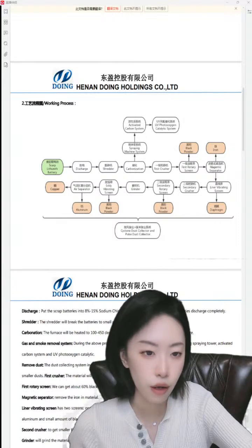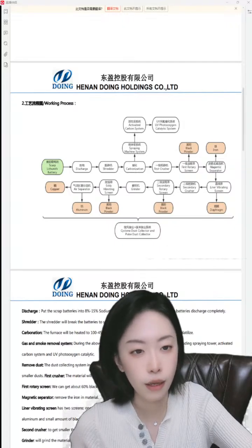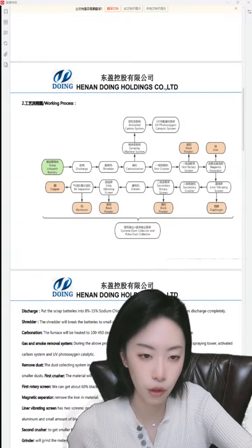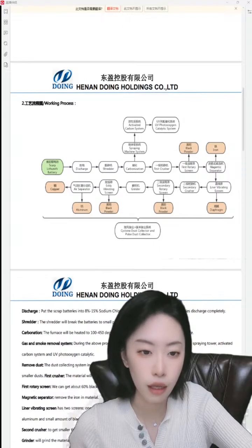Then they will go into the vibrating screen. Use vibration for screening. Different products can be controlled by multi-layer screens and discharged from their respective outlets. The two layers of the screen mesh are 2 mm and 100 mesh stainless steel wire mesh. And the top layer of the screen is a diaphragm equipped with pipes and fans to remove the plastic diaphragm. And the middle layer is the copper, aluminium, and black powder. The bottom layer is a black powder, and the recovery rate of the diaphragm here is about 98%.